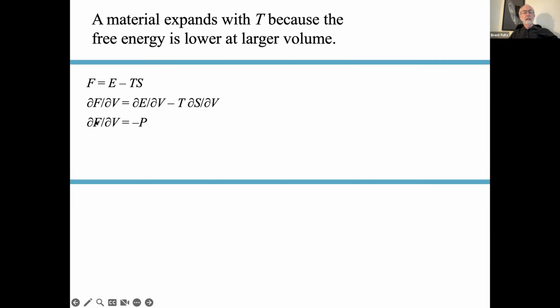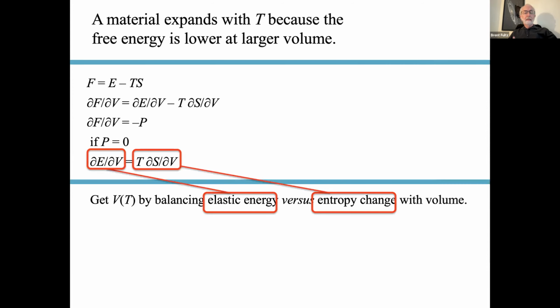How does the free energy change with volume? So if the pressure applied is 0, then these two terms have to be equal to each other. And this is a condition that we're going to be using to get the volume at a given temperature. Okay, so basically thermal expansion matches an elastic energy of stretching the lattice versus the improvement in entropy that you get by, say, lowering frequencies with the increased volume.